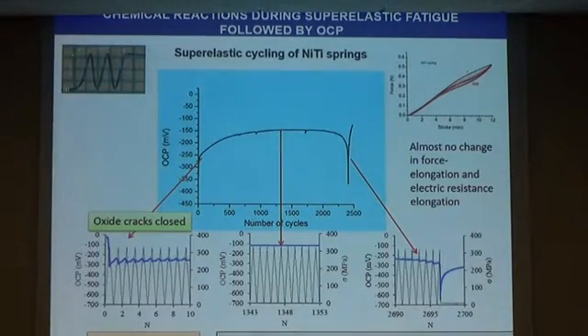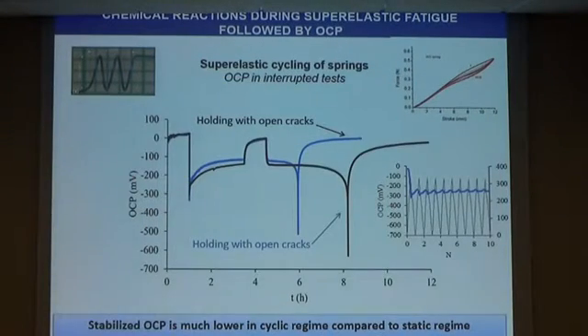This is on the spring, because we also worked on springs. With a spring, you can have a gradual increase. You don't have these shear bands. And this is the OCP response upon cycling. Again, you have the drop here, and then periodic cycling. Here there is some kind of repair of the surface in corrosion terms, then stable behavior, and when finally the cracks start to grow, 1,000 cycles before, you see this decrease, which is the evidence of a few suddenly selected fast-growing cracks. You don't see anything in the mechanical or electrical response, because it's really localized to the surface.